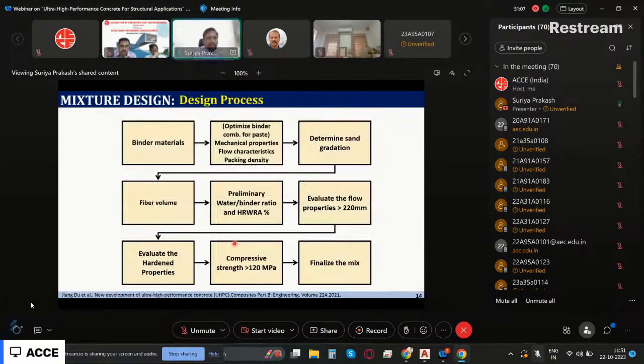Okay, so we select the binder materials, and then first we do the optimization of the paste, without any fine aggregate. So first we optimize the binder combinations for paste. That means how much should be cement, how much should be GGBS, how much should be silica fume, how much should be fly ash. I make a paste out of it and then evaluate the mechanical properties and flow characteristics and packing densities.